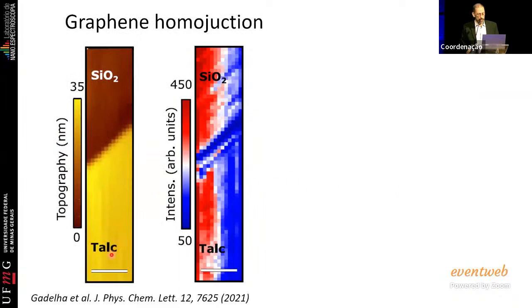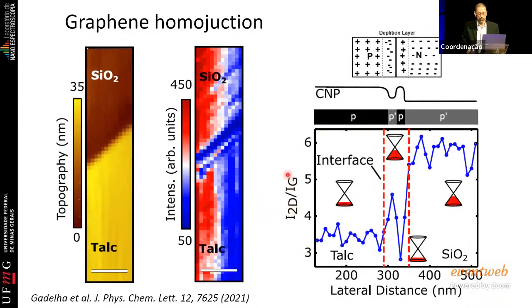And if we now go with the nano optics, the image you have here, the graphene is on top of talc, and here the graphene is on top of SiO2 or glass, okay? This is on a glass cover slip. And this image that you have here is the topography, is the AFM, because the nano antenna, at the same time that it is doing the nano optics, is also doing atomic force microscopy. So you measure here the difference in height, so you know that the junction is here. And now if I measure the intensity of a given peak, I see that there is intensity oscillation when I cross the junction. And if I make a plot here of the intensity ratio between these two specific peaks, I'm not going too much into details, you see that this intensity ratio goes up, down, up, and then is stable. And what you are doing here is directly imaging the depletion region of this P prime homojunction.